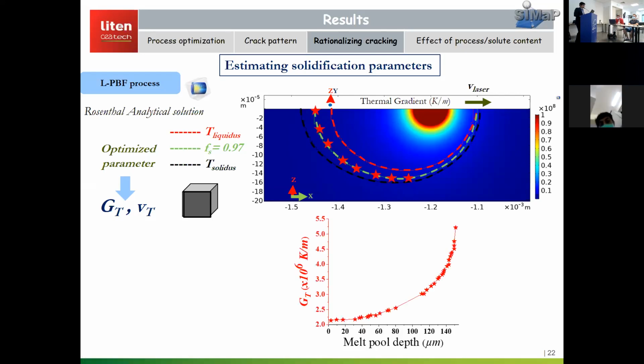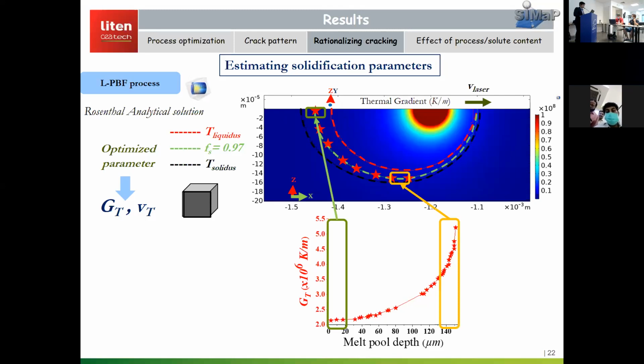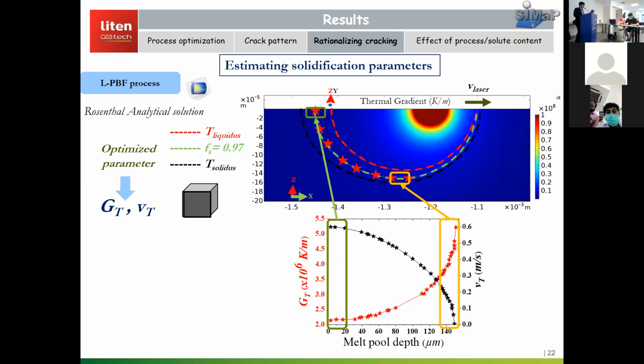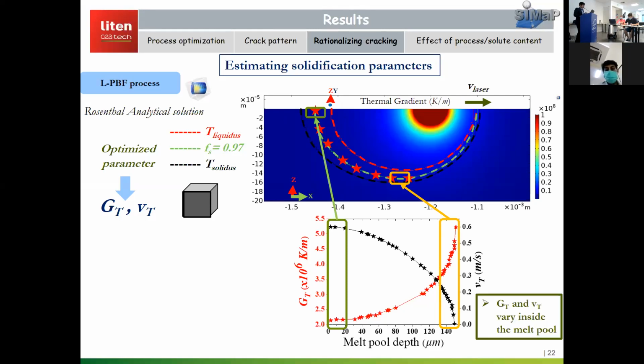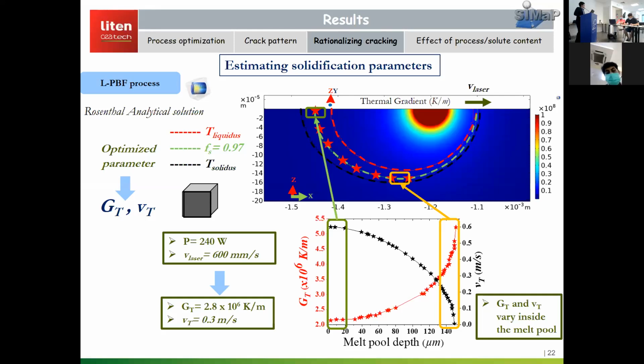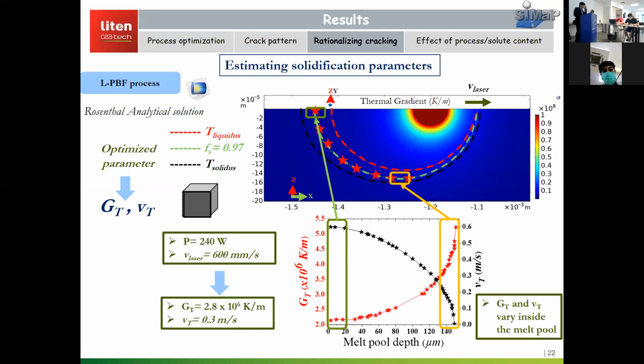We estimated the thermal gradients along the coalescence solid fraction as a function of melt pool depth. We clearly see that the thermal gradient increases as we go into the depth. Lower in the melt pool we have higher thermal gradients, and above we have low thermal gradients. But the solidification velocities are completely different in nature; it is inverse. At the bottom you have low solidification velocity, and at the top you have high solidification velocities. So these parameters vary inside the melt pool. We thought, okay, for a given laser power and laser speed, let's just take the average values along the melt pool and use them in the model. This is how we obtained the thermal gradients and solidification velocities.